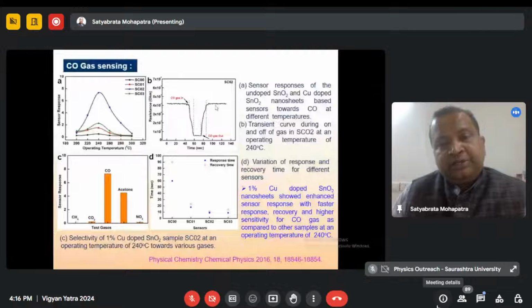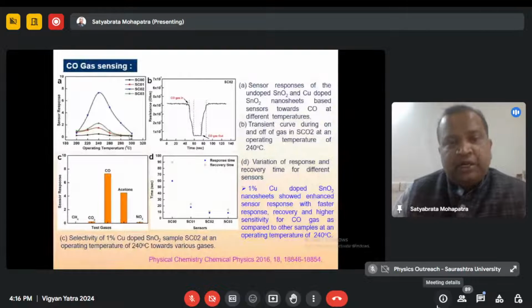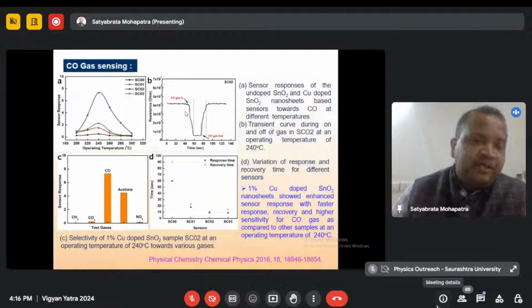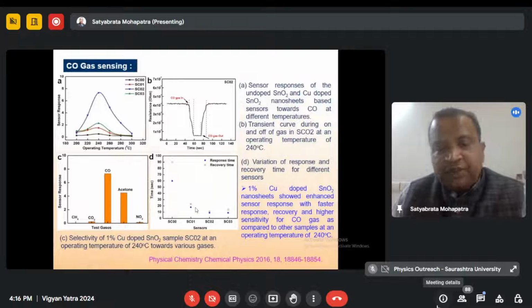And in B, you can see the transient curve, which shows how the resistance varies during gas in and gas out. It gives an insight into the response time. You can see that the response and recovery time varies when we dope copper. There is a significant decrease in the response time and recovery time, which is required for gas sensing.